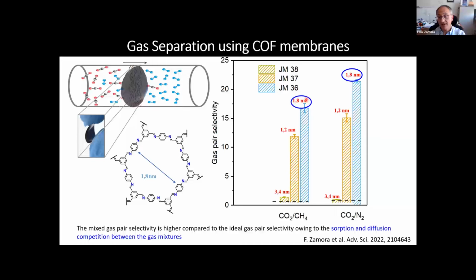Because in that case, we think that we have a nice interaction between the CO2 and the nitrogen of the imine structure, chemical sorption. We have chemical sorption, but still we have room for the permeability of the methane and nitrogen. And this allows us to have this nice gas pair selectivity.